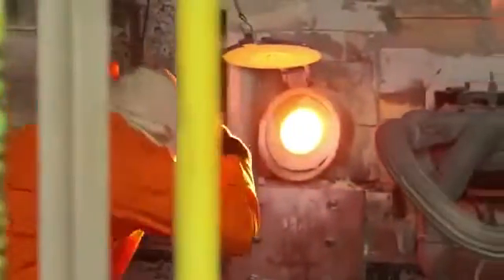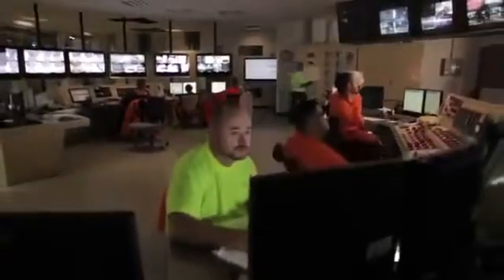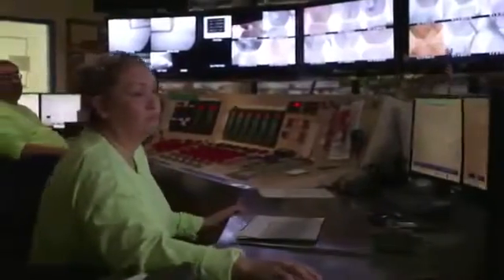Natural gas, burned in preheated combustion air, then heats the batch up to 2,800 degrees Fahrenheit. Once heated, the batch materials melt and change from a semi-molten state to molten glass. Melting, refining, and homogenizing take place within separate zones of the furnace. Processes within the furnaces are managed from the control room to ensure that the glass is homogeneous and free of bubbles.